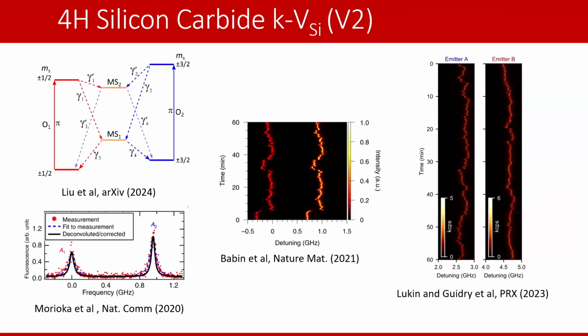Excellent. So the silicon vacancy is the color center of choice that I have been working on in Yellen's group, and that's primarily because of its interesting level structure and its excellent wavelength. It's a very convenient wavelength for working with lasers. We have tunable lasers. These optical transitions are there too, because it's a spin 3/2 system. Optical transitions are at 916.4 nanometers, which is convenient for scannable, tunable lasers and for optical fibers, etc.